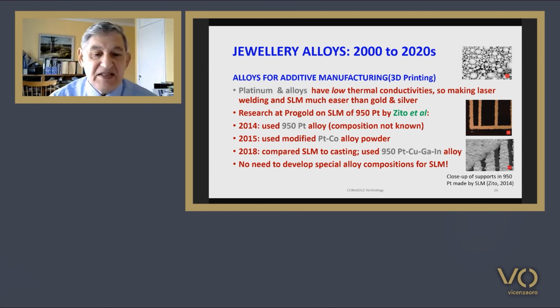In 2018, their study compared the selective laser melting process to the same components made by investment casting, and in that they used a platinum copper gallium indium alloy. What became clear from all of these studies is that it is the manufacturing process that matters, and there is no need to develop special alloy compositions for selective laser melting, which is in contrast to what we've seen for gold.